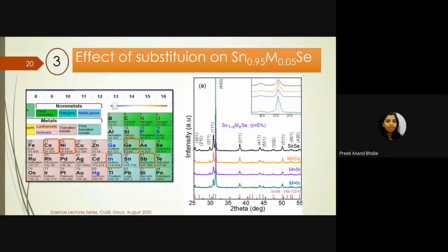So what choices does one have to replace this Sn? I could put in Sb, antimony, which is the neighbor of Sn, or one could go for germanium or indium. And if one wants to see the effect of copper in the system, instead of copper could I put nickel or cobalt? These are the obvious questions which come to mind. Based on this, when we prepared the 5% samples, we realized that antimony or germanium is not a good choice at 5%. Germanium does not go beyond 3% in SnSe without giving an impurity phase. The same is the case with Sb. It forms another secondary compound with selenium. So what we are left with are the very limited choices of indium, nickel and cobalt, which will give you pure systems.